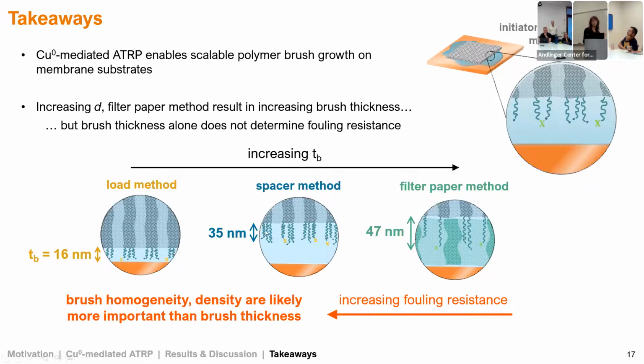However, we maybe are getting brush growth just into the pore space, because the thickness of the brushes is orders of magnitude lower than the pore width. So I'm not sure how to actually characterize that yet, but it is interesting. And there is a paper looking at a different method for ATRP that discussed actually driving interpore brush growth as a way to get better fouling resistance, because you don't want irreversible fouling inside your pores.